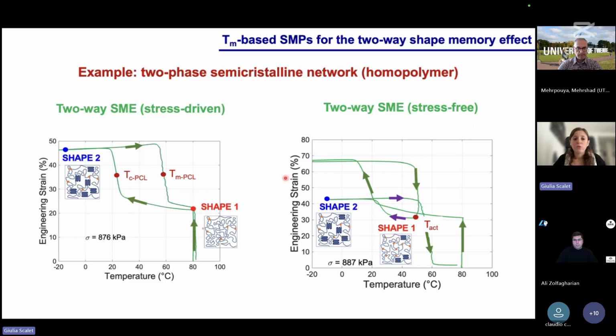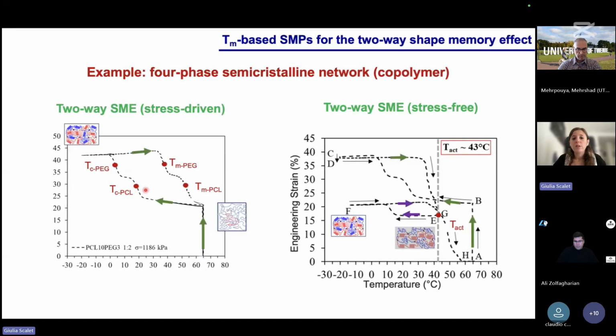So this is an example of the two-way memory effect for a network made of just one polymer, and you can see that it can express this two-way memory effect under stress-driven and stress-free conditions. So it is very advantageous for different types of application, and you can see that there is this reversible passage between two deformed shapes upon cooling and heating cycle, passing through these melting and crystallization temperatures. And the same happens if we consider, for example, a network made of two copolymers. It is the same thing, but we have more polymers and so more crystallization and melting temperatures in order to achieve also reversible but also sequential shape changes.